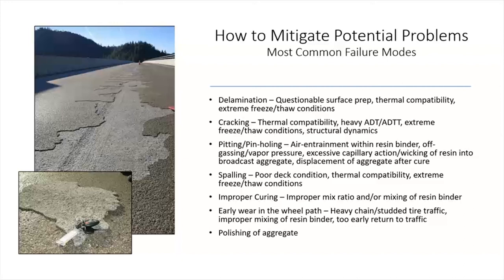This is also interesting. Right around the cold joint, the center line, is where this delamination started. These thin overlays, or any type of overlay system, want to pull up. There's greater shear forces if you have a crack, or let's say a cold joint in a weak area, you have this unzipping effect. And it's a perfect example of that unzipping effect. There was a cold joint down the middle. The material was put down really thick, with a lot of freeze-thaw. The surface paste should have been removed a little bit better, and the surface paste was weak enough that it pulled up.